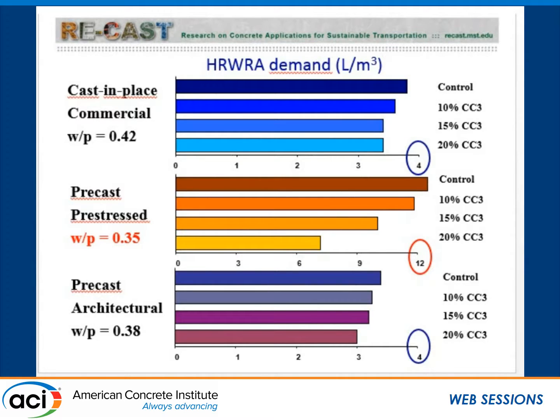We get a very slight reduction of superplasticizer. And in the case of the much lower water to powder ratio, where you have a higher amount of powder and less water, the use of calcium carbonate allowed us to reduce significantly. So here you have 12 liters per cubic meter, going to about 7, 8 liters per cubic meter after 20% replacement. So that has significant implication on strength gain, but also on cost. For the architectural application, it was a type 1 cement. You see, again, there's really hardly any difference in terms of the superplasticizer demand.